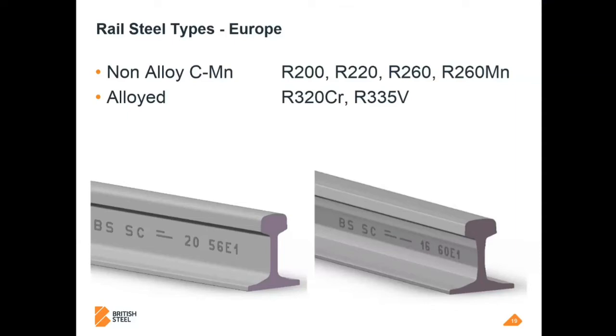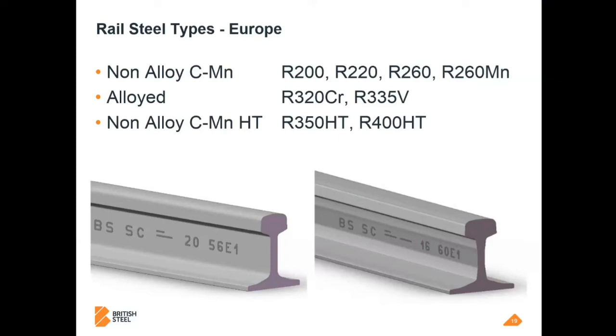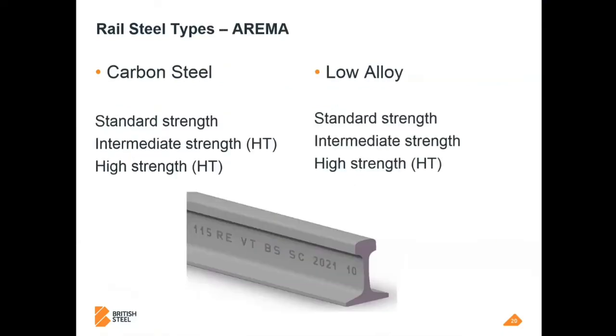We also put in that bracket HP, although technically it's microalloyed and it's a bit of an outlier. It sits outside the normal design philosophies. Non-alloyed also comes in a heat treat variant, and alloyed comes in heat treat variants. So if you've got these two options, alloyed and non-alloyed rail steels, why choose one over the other? It's the same in the American specification. You have a carbon steel, which is your carbon manganese steels, and your chromium alloyed, and then a range of strength levels, which is just varying levels of heat treatment.